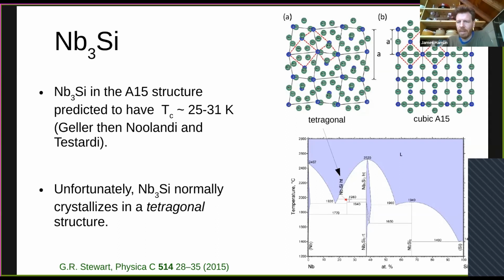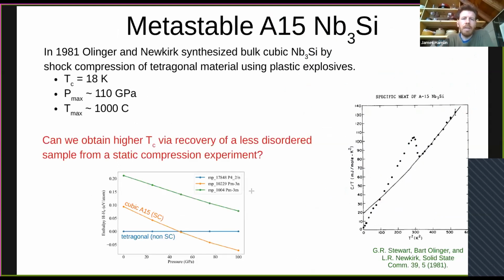If you look at this phase diagram over here on the right, if you were to anneal it at, say, 1600 C, it would decompose into niobium-5 silicon-3 and niobium. So let me talk about what we did here. In 1981, Olinger and Newkirk synthesized the bulk phase by shock compression of the tetragonal material using plastic explosives. So they basically blew up a small bomb around the material. It took it to very high pressure, estimated to be around 1 megabar, and very high temperature, around 1000 C.